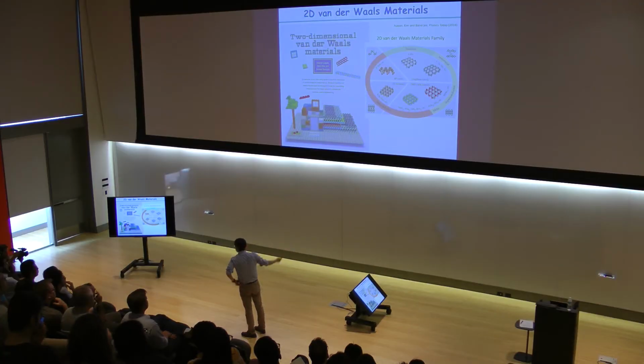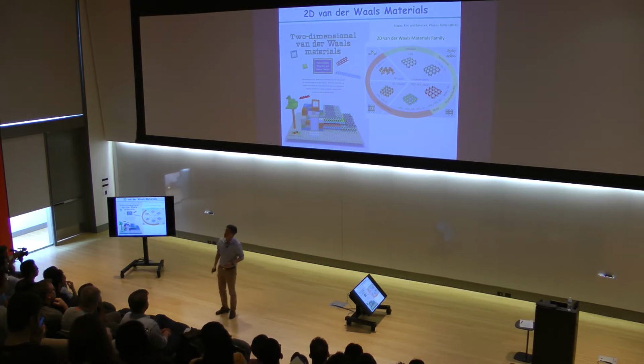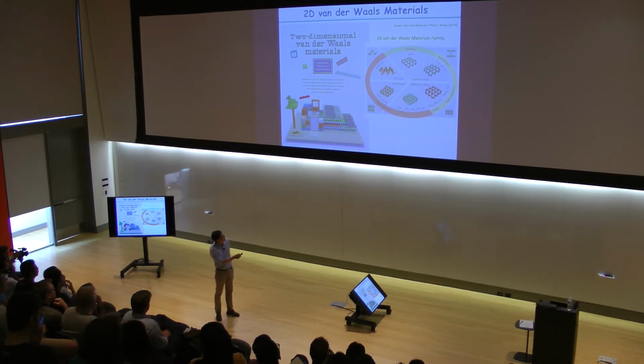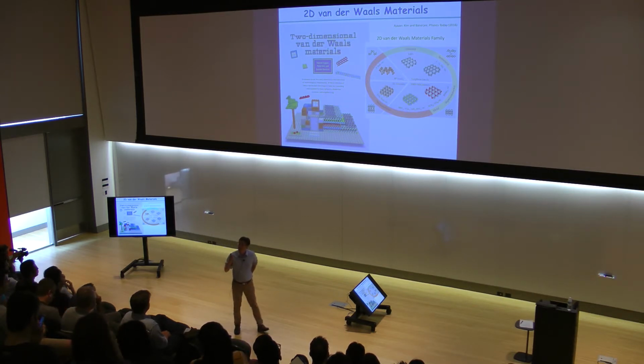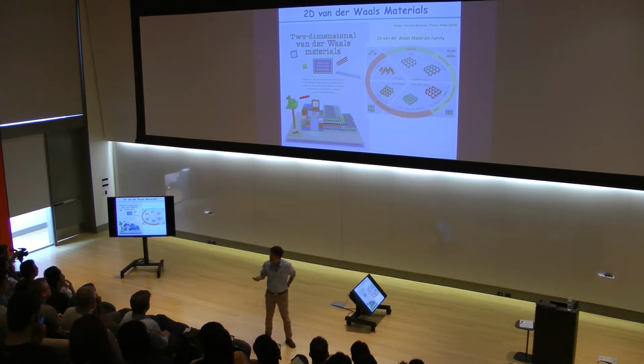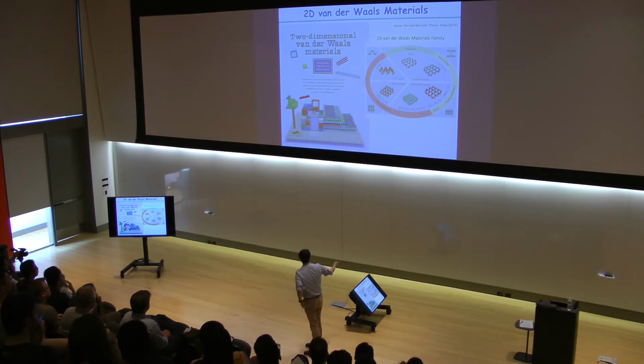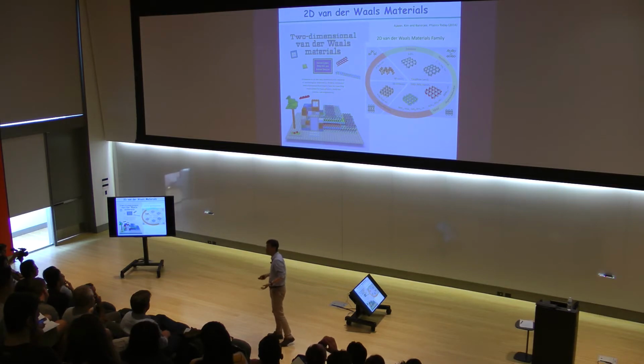But also, some of the materials become insulators. Boron nitride, which I'm going to discuss, is a good example. Or some of the materials, especially transition metal dichalcogenides, which consist of a transition metal with chalcogen atoms such as sulfur, selenium, and tellurium, often behave as semiconductors, p- or n-type, or sometimes become superconductors if you use niobium, for example. Some materials become strange metals, such as charge density wave systems. And the list actually grows every day, and we've been enjoying seeing in the past 5 or 10 years what kinds of materials we can create in the two-dimensional limit. And one can study a lot of their interesting electronic properties in this quantum limit of the two-dimensional system.